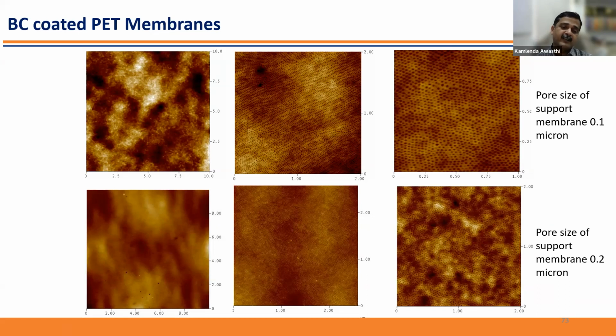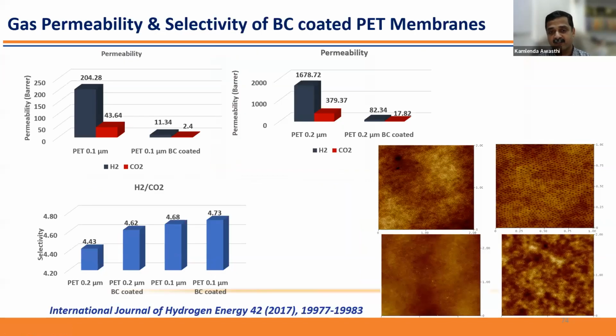So the upper layer basically helps us to get a more controlled way to diffuse the gases in these nano channels, and the supporting layer basically provides us mechanical strength. What is happening here is that because of this narrow size pore distribution, our permeability drastically goes down. So earlier it was 204 and here it's 11, 43 and 2.4. So basically this membrane is behaving just like a dense membrane.